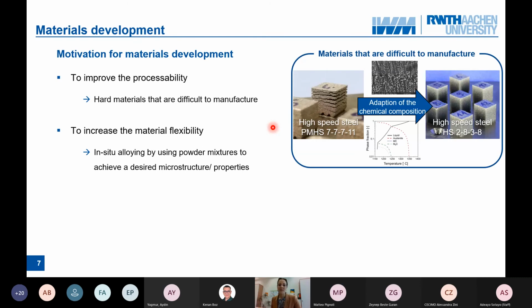So we have some materials that are not very well suited for the process. That means materials that are difficult to manufacture, like very hard materials like tool steels or even high-speed steels. And you see, due to the process, due to the very high solidification rates and the high thermal gradients in the process, you often get samples like that.